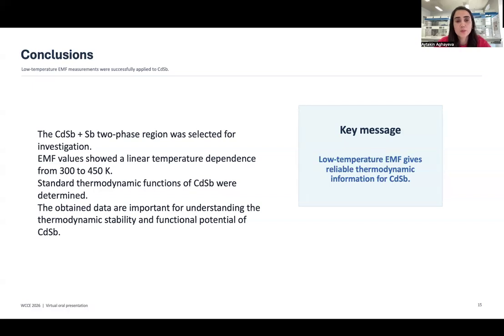To conclude, low temperature EMF measurements were successfully applied to the CdSb compound. The CdSb plus Sb two-phase region was selected for investigation. The synthesized alloys were confirmed by XRD analysis. The EMF values showed a linear temperature dependence in the range from 300 to 450 Kelvin. Using these EMF data, the standard thermodynamic functions of CdSb were determined. The obtained results are important for understanding the thermodynamic stability of CdSb and its potential as a functional thermoelectric material. The key message of this work is that low temperature EMF measurement provides reliable thermodynamic information on cadmium antimonide.